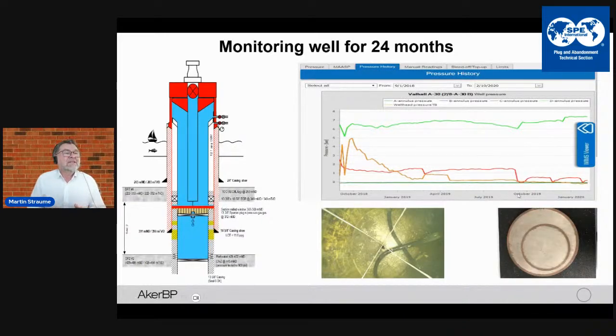So this again shows how we actually removed the tubing pressure. The tubing pressure was coming down and going to zero the whole time. The C annulus pressure was actually coming down each time we bled it off. It built up to a lower level, and eventually it became zero. And this is what happened in the video you just saw, that it takes some time to actually remove the gas that is captured within the cement matrix.